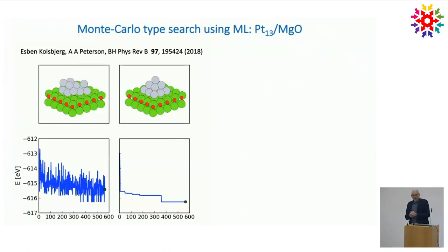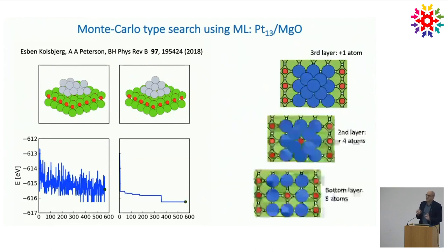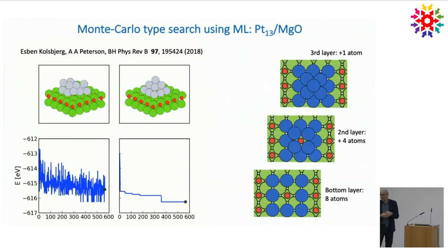And then you may say, when they did 36 different structures for platinum 13, why didn't they consider that such a nice pyramidal structure could be a candidate for the best structure? They didn't do that because it's a hollow pyramid. And humans normally don't think that metals, or small chunks of metals, could be hollow. Or chunks is a big word in an institute like this. So nanoparticles, people don't think that metallic nanoparticles could be hollow. But it actually turns out that the preferred way of organizing 13 platinum atoms is as a hollow pyramid.